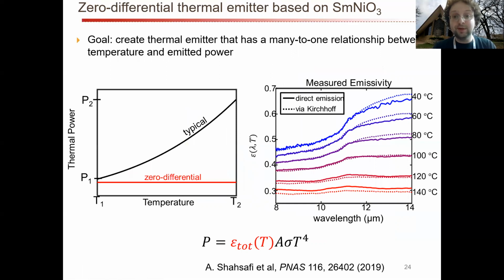Fortunately, we were able to do this with a samarium nickel oxide film on top of an appropriate substrate with an appropriate thickness and so forth. This is the measured emissivity versus wavelength versus temperature. You can see it's this nice gradual decrease that matches the Planck distribution quite well.